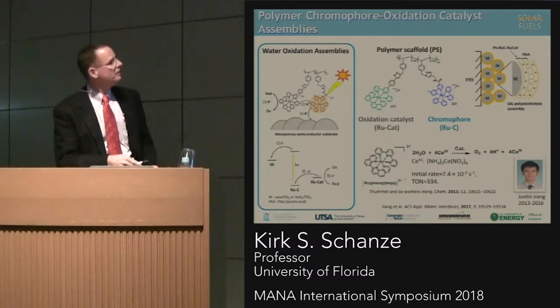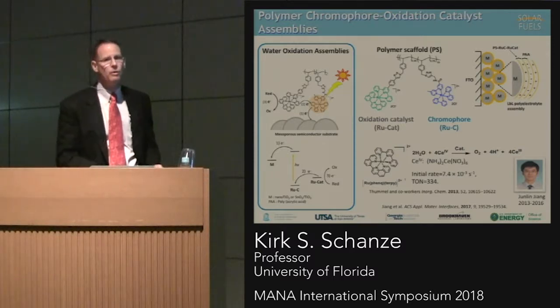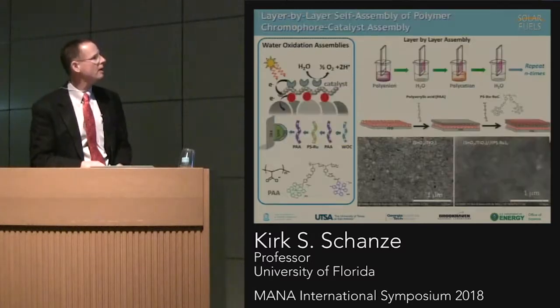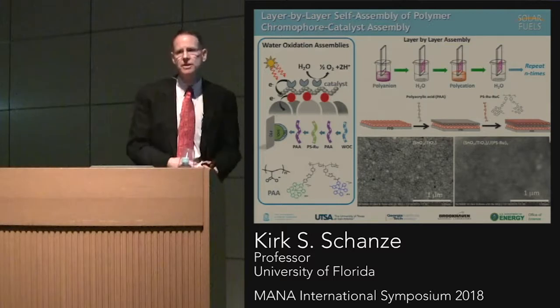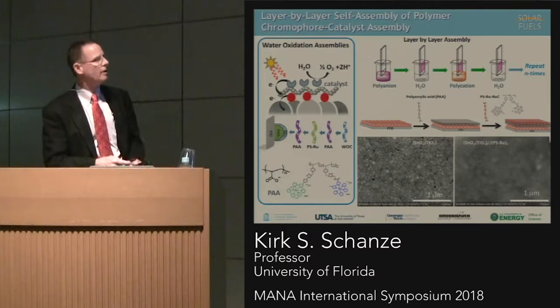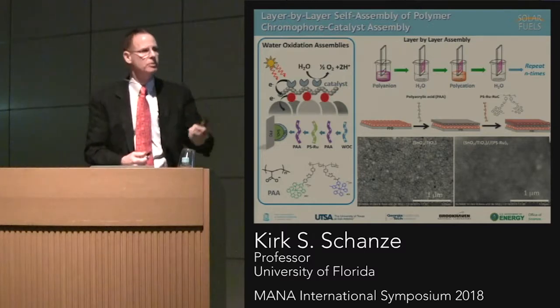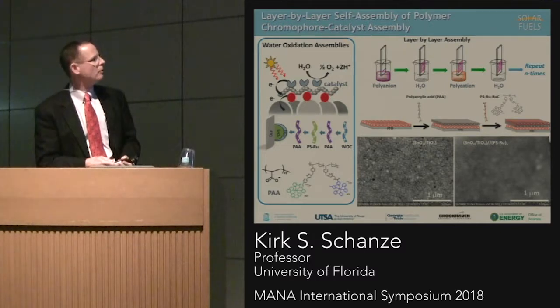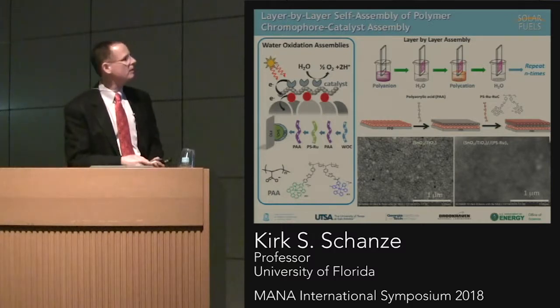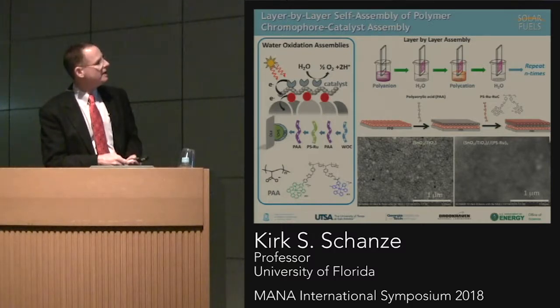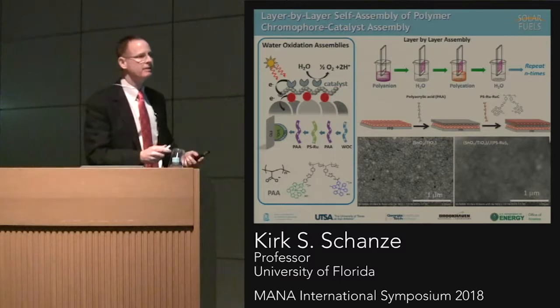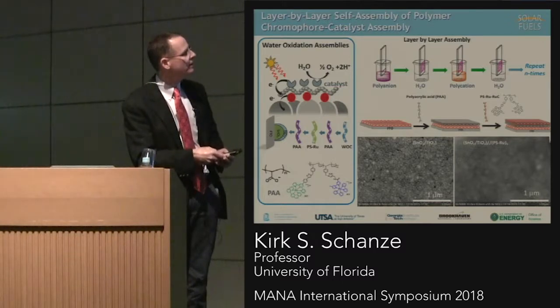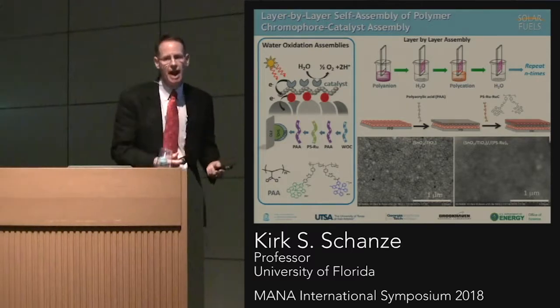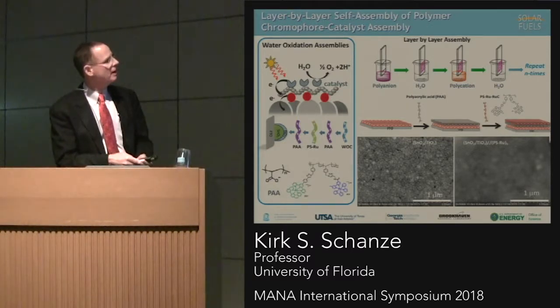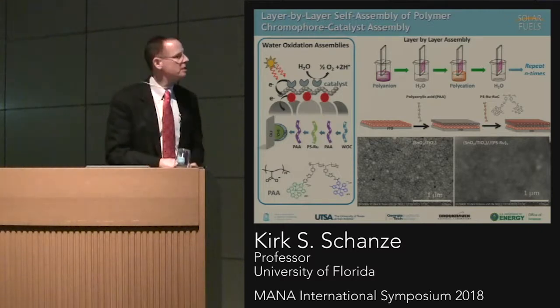You'll notice that in this system we don't have anchoring polar groups, which I've alluded to several times in my talk. So Junlin had to develop an alternative strategy to make films with these systems. To do that, we used the so-called layer-by-layer technology, which is used widely by Professor Riga here at Mana and by Gero Decher, who developed it in France. The basic idea is that you take two oppositely charged polymers. In this case, we just use polyacrylic acid as an inert, negatively charged polymer. The ruthenium polymers are actually polycations. So we can alternately deposit these two polymers and build up what we call multi-layer films.